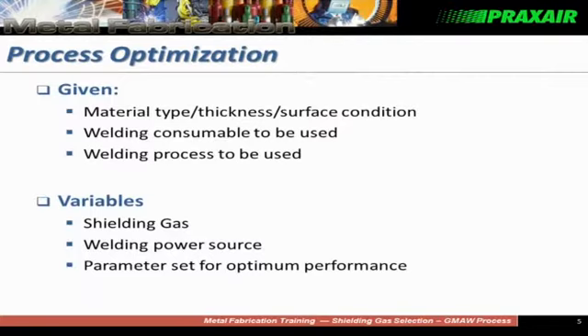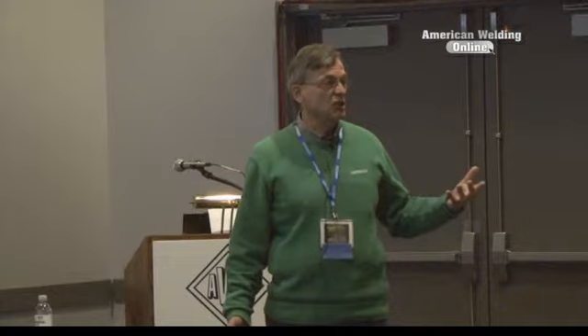And typically, you'll have decided on the process based on the equipment. If it's flux cored or solid wire, it could be a globular type transfer depending on the shielding gases you use. With solid wire, it could be spray transfer, it could be short circuiting type transfer, it could be pulsed metal transfer. So the equipment will obviously determine to a degree the process we can use. But some of the variables we don't often look at